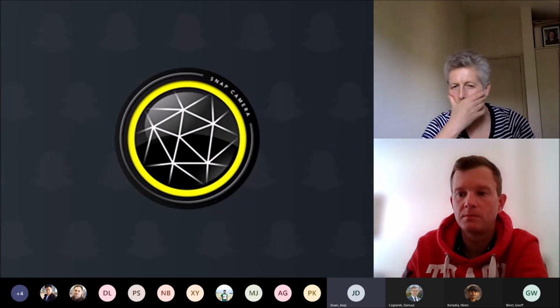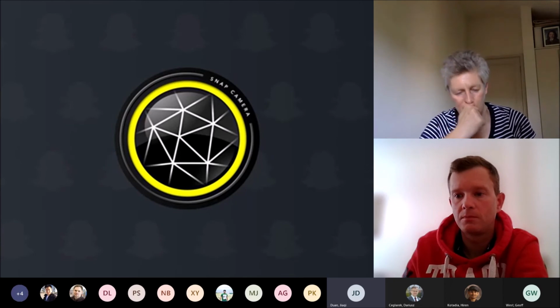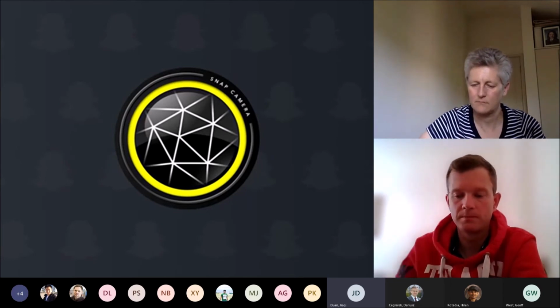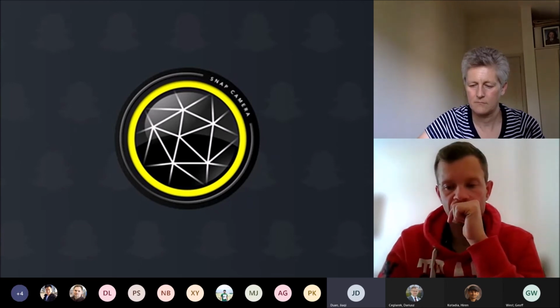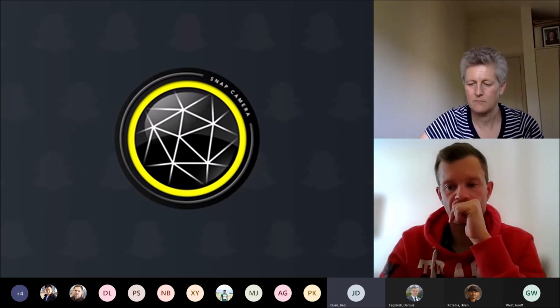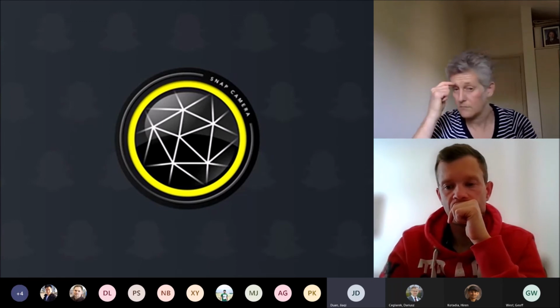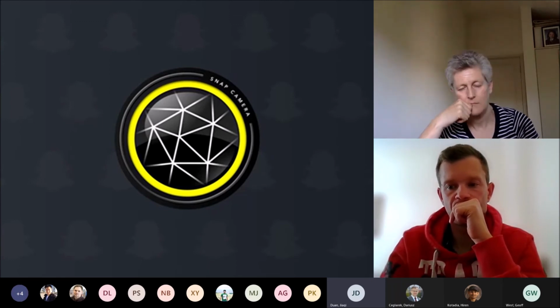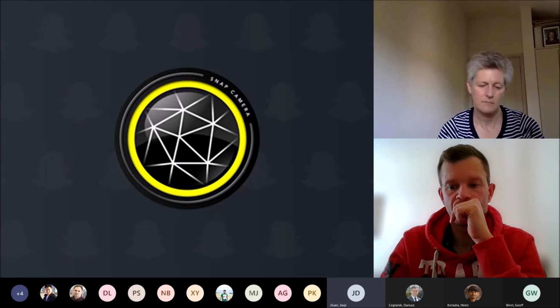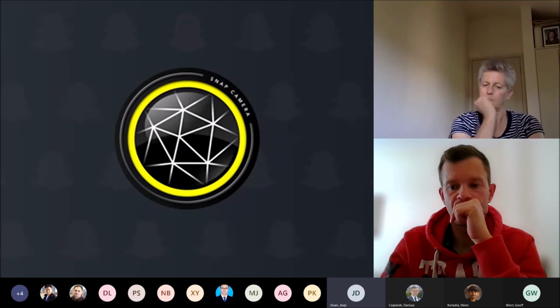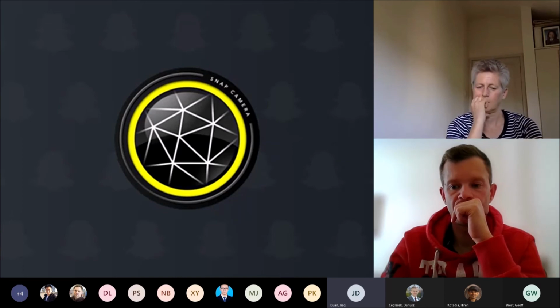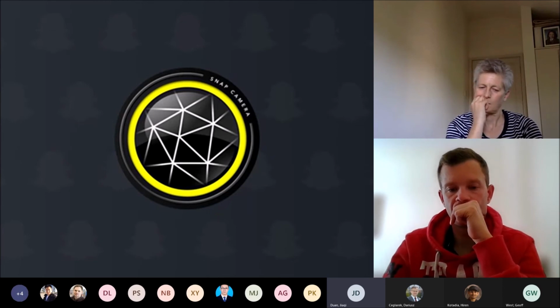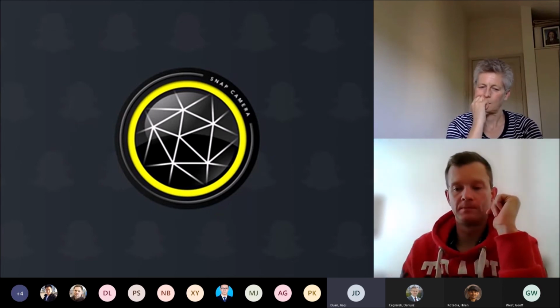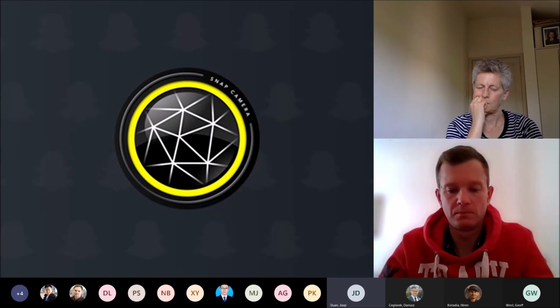So your idea of the growth of Goss is because of the distortion, because of the silicon. But my question is why it doesn't show up the distortion effect during the primary recrystallization? I mean, at the early stage. Even at a later stage, if it grows larger, it will have a size effect. No matter which orientation it is, it will more likely consume the surrounding smaller grains. So for your theory, I'm still struggling to understand why the effect of the distortion doesn't show up at the very beginning from the primary stage. Thanks. Thank you for the question.